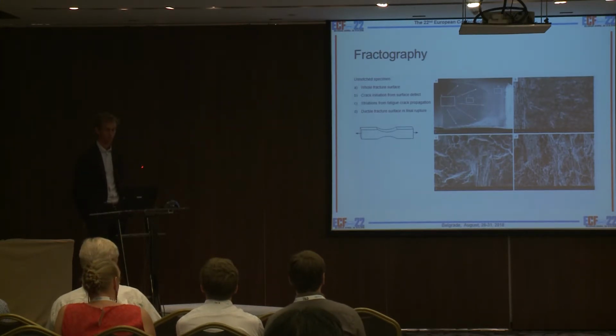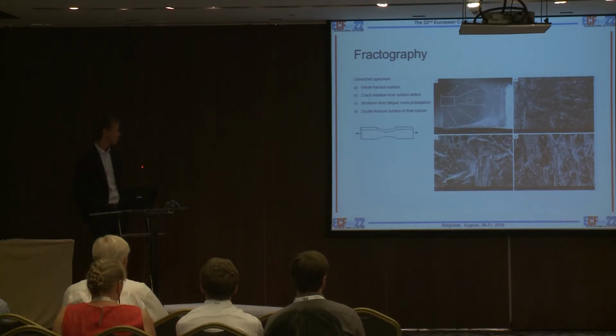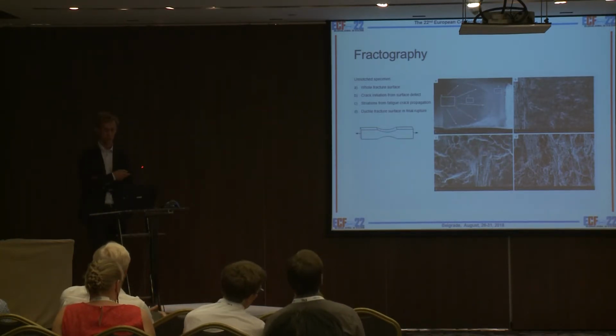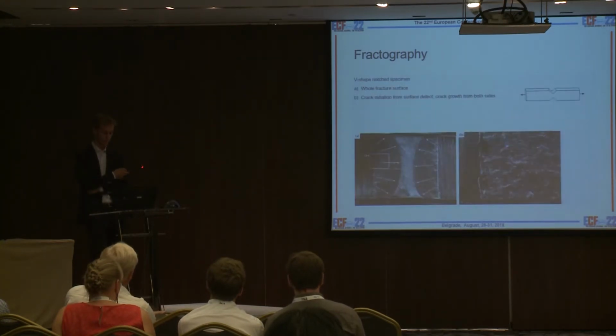This is the unnotched specimen. The crack is propagating from one side with first striations, and then the final rupture is ductile. But it's from one side, so there is not a lot of effect from both sides.